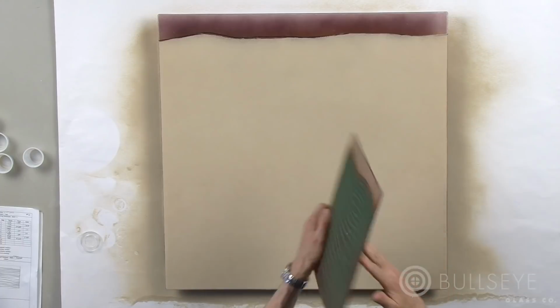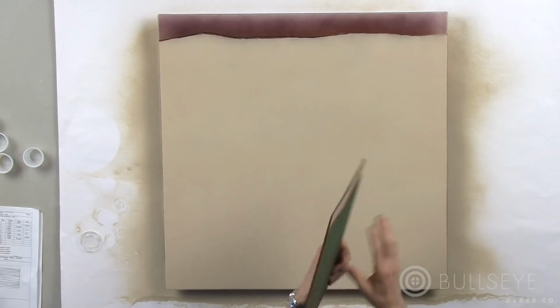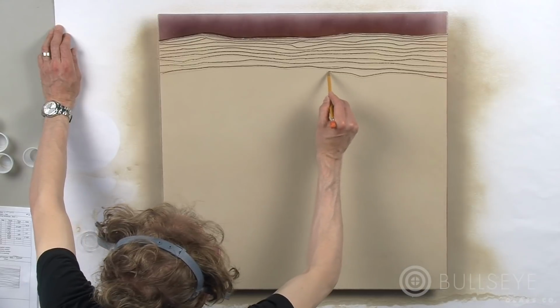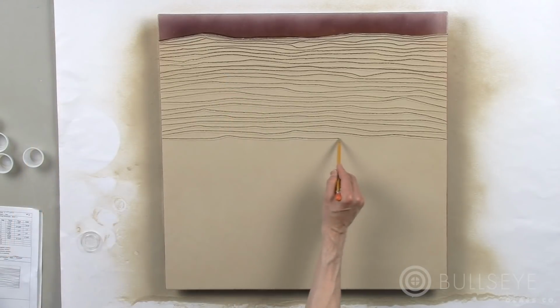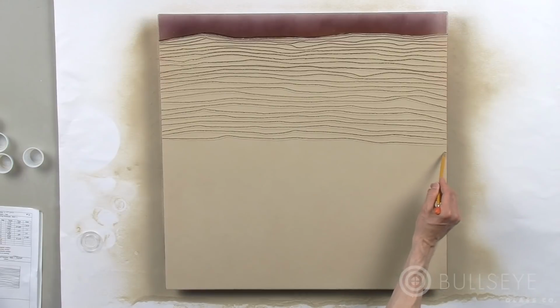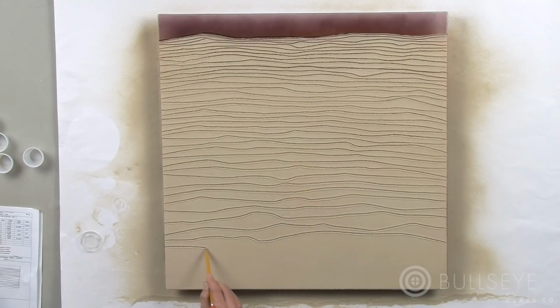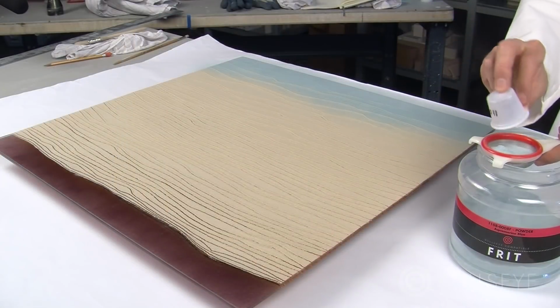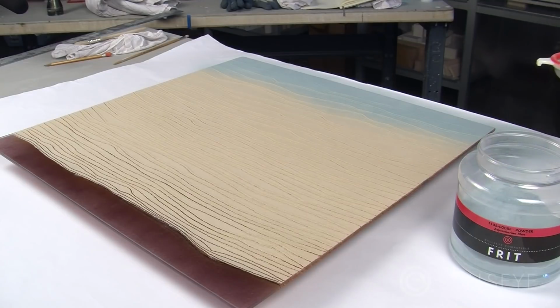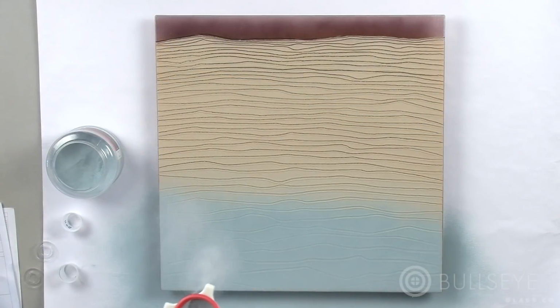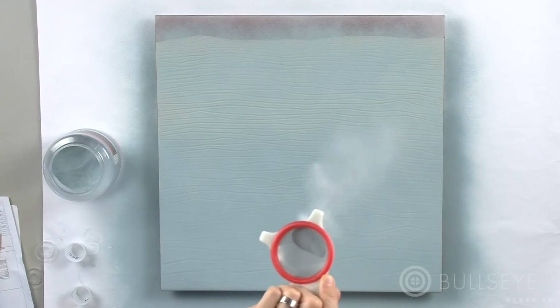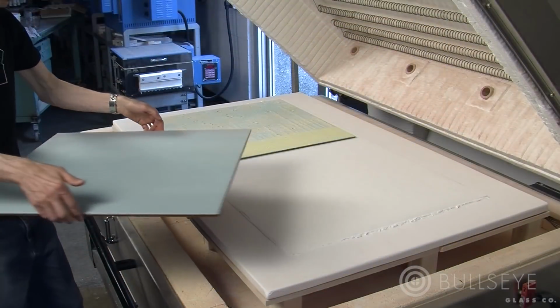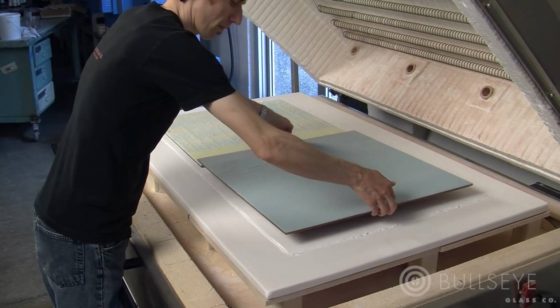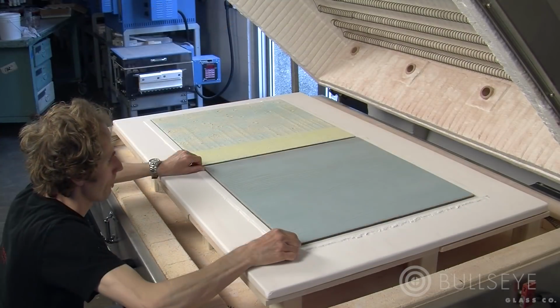And what I'm doing here is I've decided that I actually want to deviate from the maquette because I had just made another piece that was actually quite similar to that. So I've chosen a different tool to mark the lines into the powder, in this case the finer pencil. And now I'm going to go over that whole thing with about 10 cups of 1108, which is the aquamarine blue. And I'm applying it heavily on one edge and fading as I move towards the top of the composition. And you'll see that after the piece is fired.